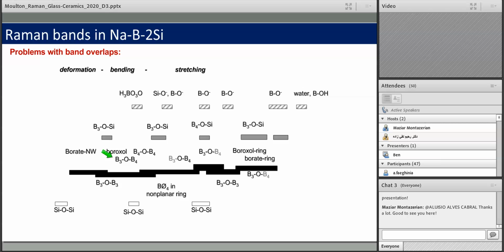That being said, it depends on a couple of things. First, B3 trigonal boron is usually only found at low borate contents. If I remember correctly, the limit is around 30% or 25%, somewhere around there. At higher concentrations of modifier, you only get tetrahedral boron. But I would have to see what compositional suite you're talking about. It is certainly possible for some compositions to differentiate between BO3 and BO4. But if you have a really complicated composition, sometimes the vibrational modes can merge together and just look like one big broad hump, in which case you cannot. So hopefully that answers Naji's question.